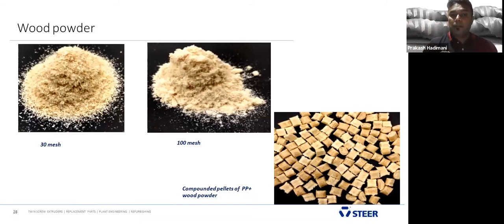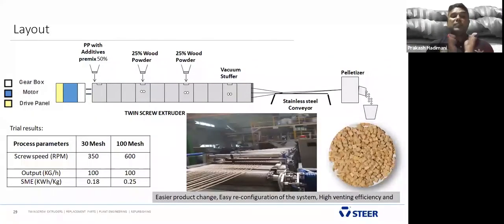Okay, this was the setup. We fed polymer from the intake, melted it completely, making sure the polymer was 100% molten, and fed the wood powder 25% and 25% in two side feeders, and used a strand cutting method. There is no water contact, and we cut hot pellets. The screw speed was 350 to even 600 RPM. The throughput was 100 kg in the 40 millimeter extruder.